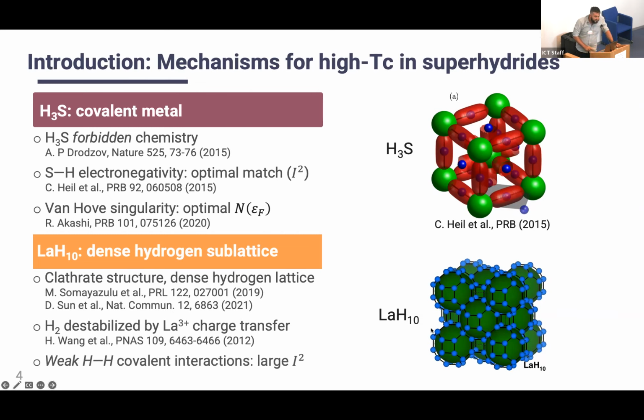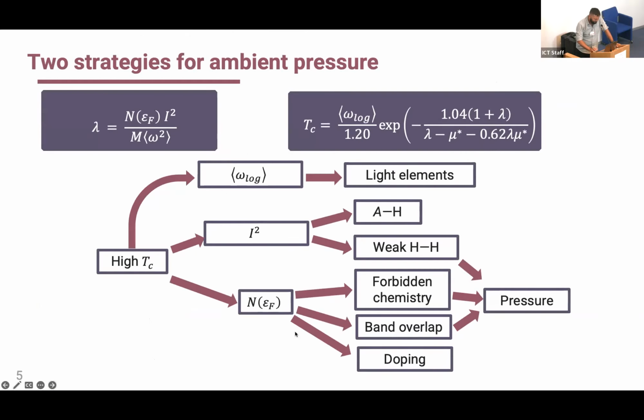And in this case, what we have is covalent hydrogen-hydrogen interactions that are not as strong as in the H2 molecule, which has a closed shell and would give us an insulator. Instead, we have a sort of in-between, which allows us to have a covalent interaction with hydrogen, which gives us the large matrix element, while still retaining the metallic properties. So with this bit of introduction, I wanted to give you a summary of many possible pathways that lead to the high TC.